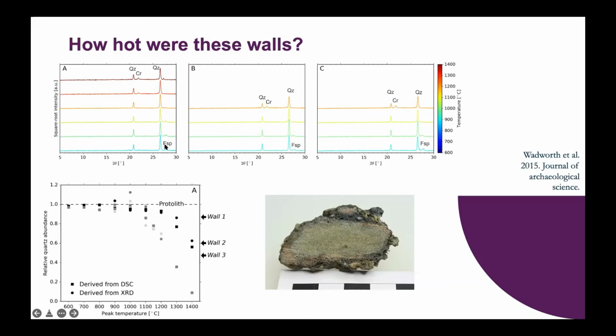Similarly, we see the feldspar peak disappear almost at lower temperatures and is gone by high temperatures. We know the relative quartz abundance of the material from the walls themselves, and so we can compare our experiments with the wall material. And so this points to equivalent temperatures between 1100 and 1200 degrees Celsius, which is the kinds of temperatures that sustained hardwood fires can get to.